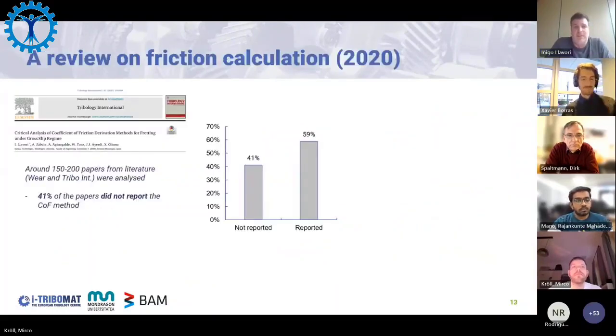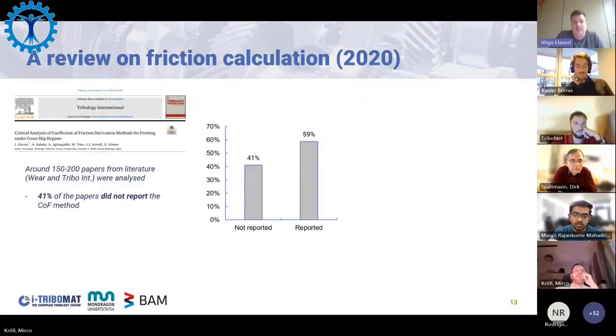So one of the byproducts of my PhD was that we decided to write a review paper on which methods we can find in the literature and what people do. We read around 100 papers, and we did some statistics. We found that 41% of the papers did not report the friction coefficient method. They were just saying that this is the friction coefficient and that's it. And then from this, almost 60% of the reported data, if you can click one more time.